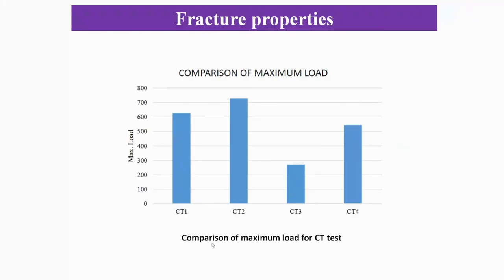For the CT test, we use the same thickness that was recommended from the thickness study curve on the previous slide. And as you see over here, the value of load to start crack propagation in the specimen. Using these values, we can determine the value of fracture toughness for the CT specimen.